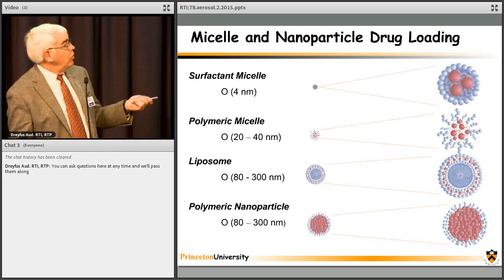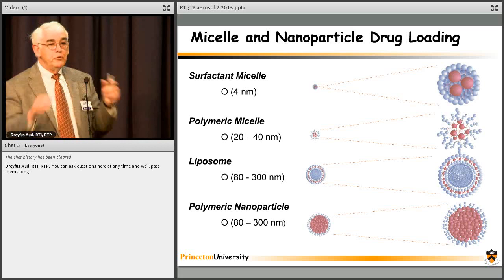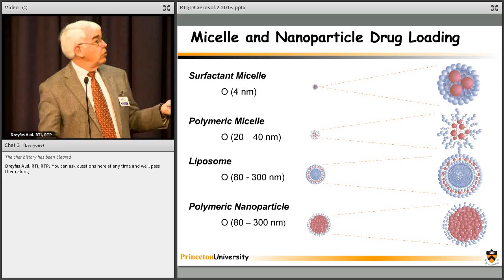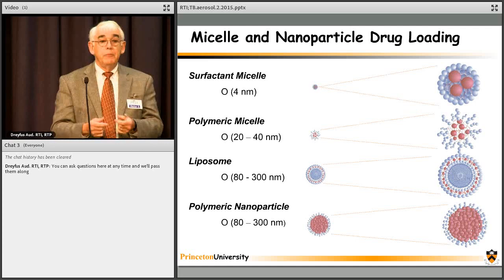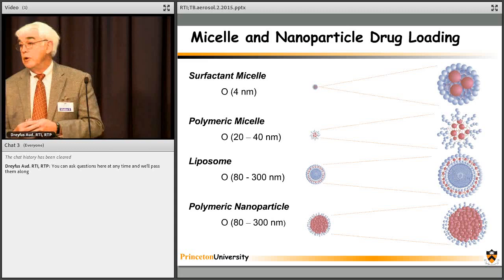Liposomes are widely used for drug delivery, and they're great for soluble species because, of course, the center of the liposome is an aqueous environment, so you can encapsulate siRNA or soluble drugs into that. But it's a terrible vehicle for hydrophobic drugs because the only hydrophobic volume you have is that small volume of the lipid bilayer. So you get very low volume and therefore low encapsulation efficiency or encapsulation amount with liposomes.